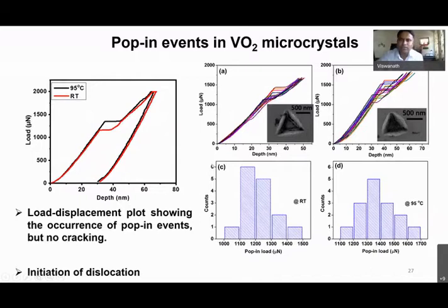And finally, we also want to see if there is something more we can extract, because it is a metallic and insulating phase. We try to look at the pop-in event. The pop-in event, of course, can be correlated to the dislocation initiation or any cracking event and so on. Of course, phase transformation information you would get during the unloading curve if it is stress-induced phase transformation.